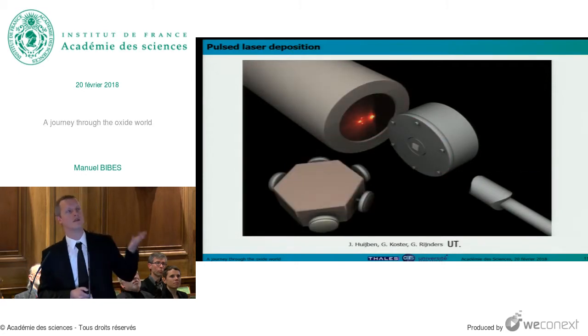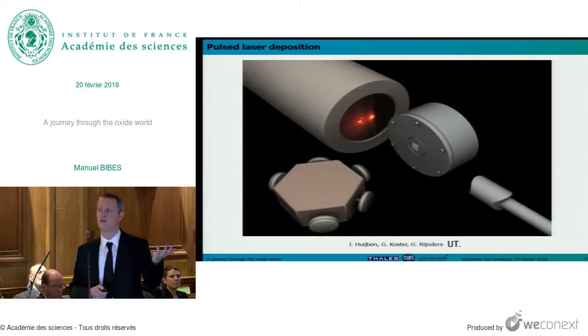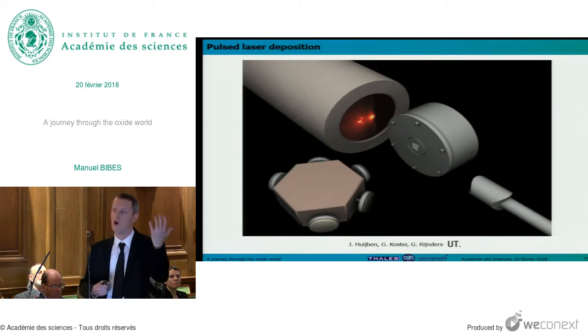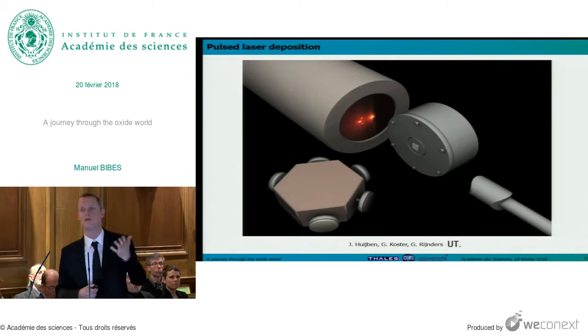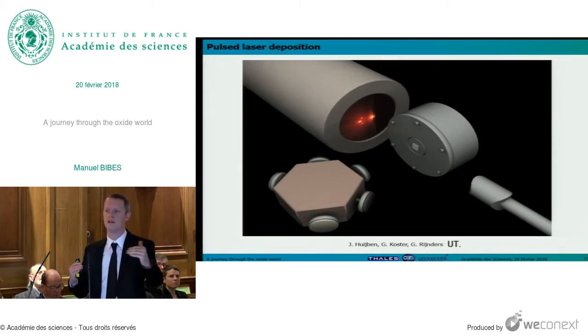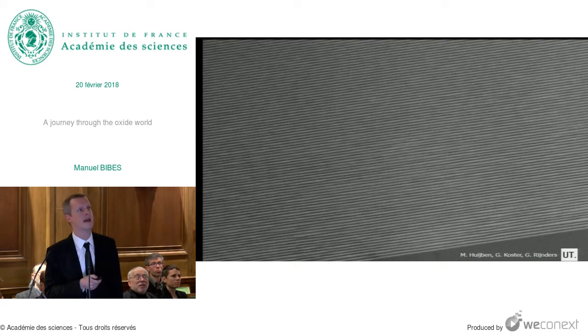And so we can hit the blue material, we can hit the pink material, so we can grow only a film of the blue, only a film of the pink, but also multilayers by alternating deposition of the blue and the pink. And in the end, this is what we get. Actually, this is a picture again from the colleagues from Twente. And you see this picture, this is not like a nice curtain or a nice piece of cloth that you would have in your house.